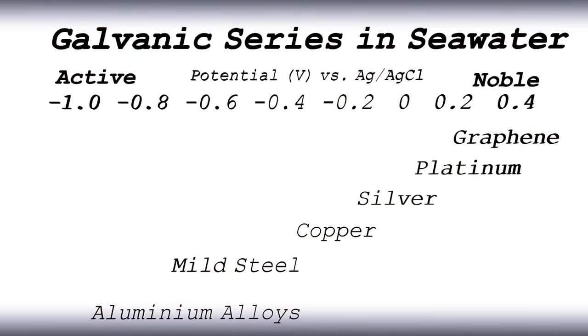As if this wasn't enough, graphene also seemed to promote the corrosion, because a galvanic couple was created where graphene was much more passive than the exposed copper in graphene's defects.